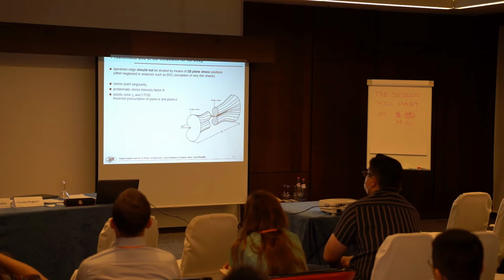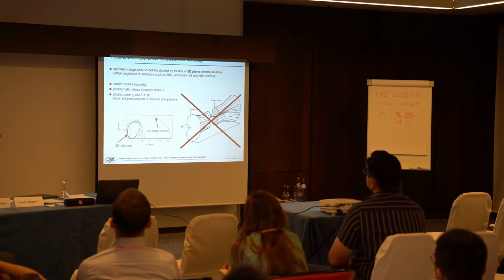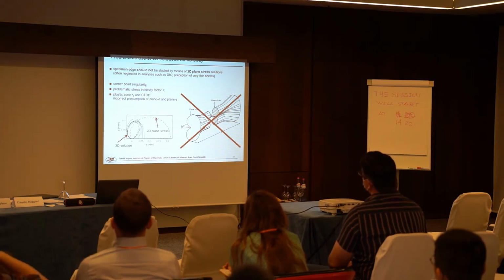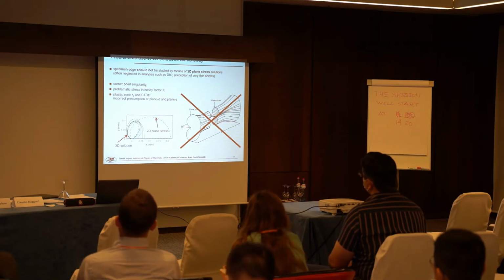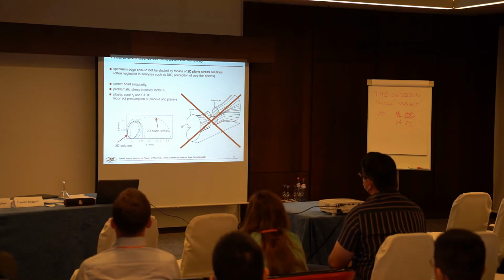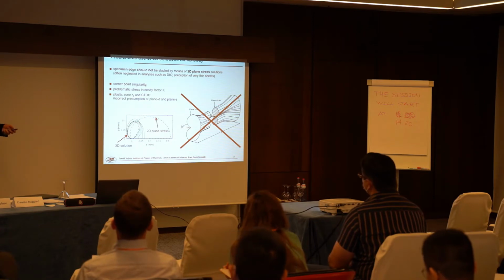apply three-dimensional simulations. So here is an example from 3D finite element modeling. All of these plastic zones are from the 3D solution at different depths of the specimen. And the other one, this big blue, is from two-dimensional plane stress solution under the same loading. So you can see that really the shape and the size is different.